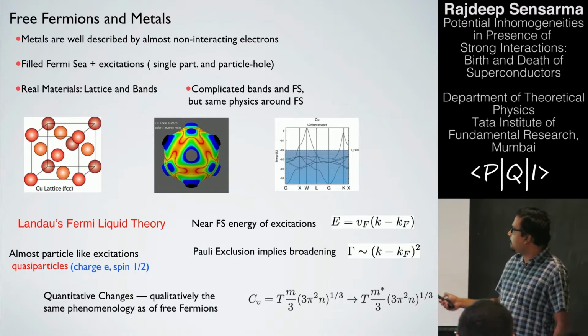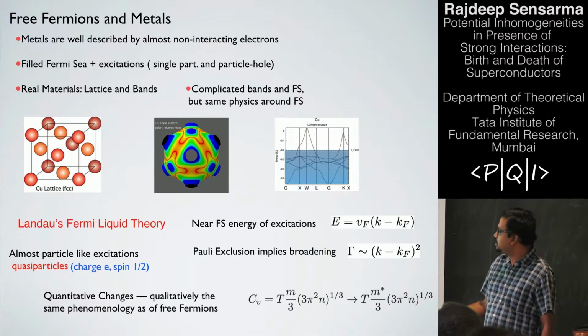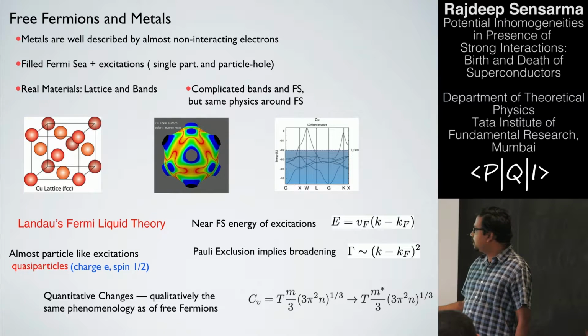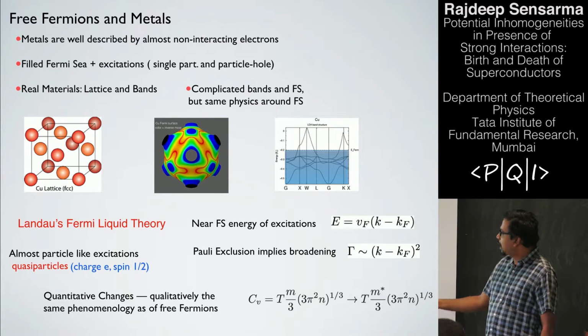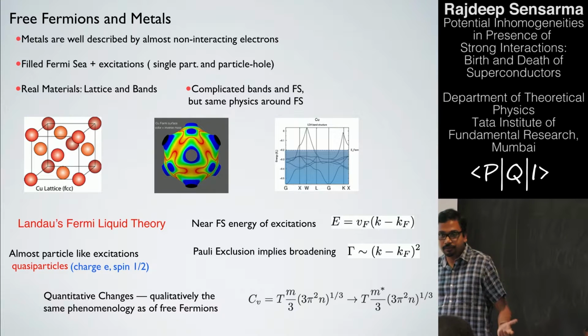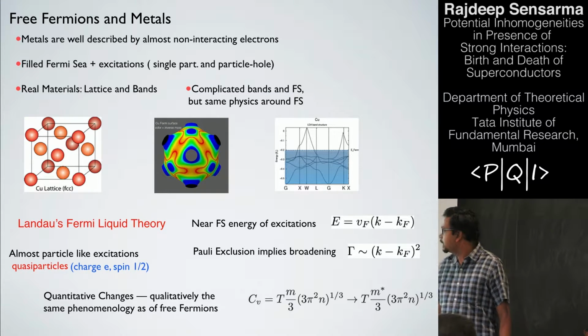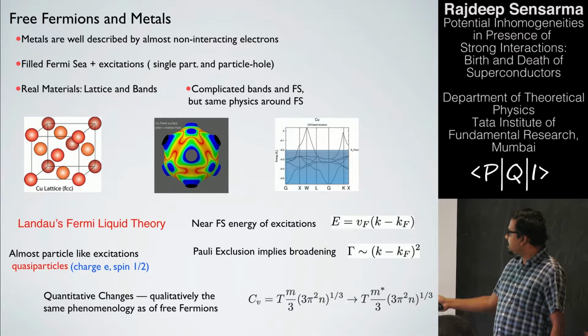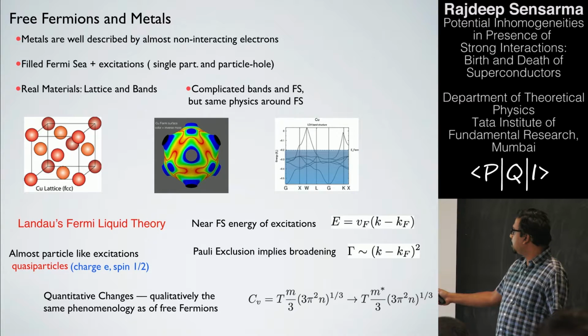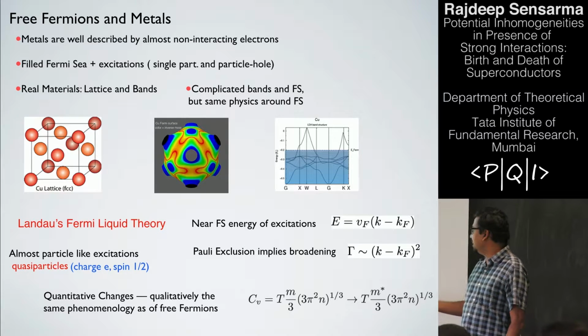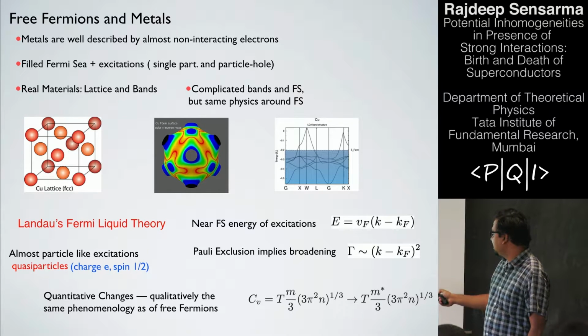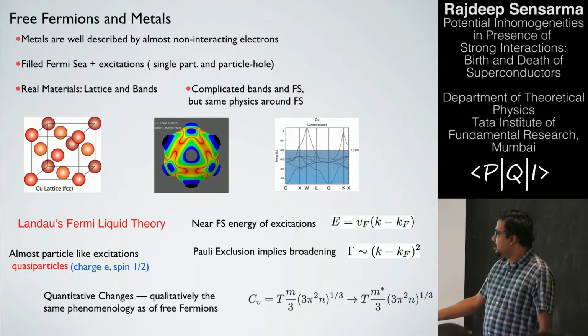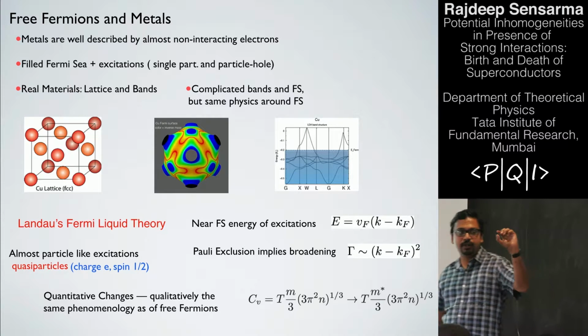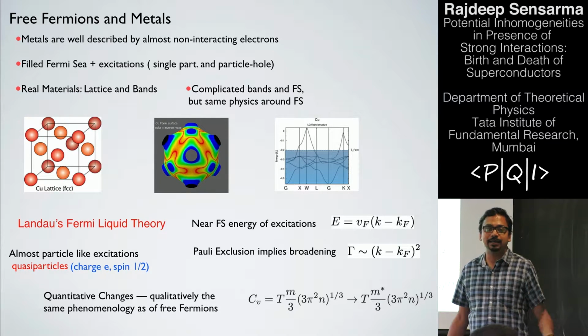Now you can ask, why does this happen? Well, electrons have Coulomb interactions, and the answer was given by Landau. Near the Fermi surface, electrons are fermions, so they have Pauli exclusion working for them. Near the Fermi surface, the excitation energy goes linearly with the momentum deviation from the Fermi wave vector, whereas Pauli exclusion shows that the width of the excitations, or the decay rates, would go as (k minus kF) squared. At least in 3D, this is exactly how it goes. Which means that as you go close towards the Fermi surface, you have almost particle-like excitations.